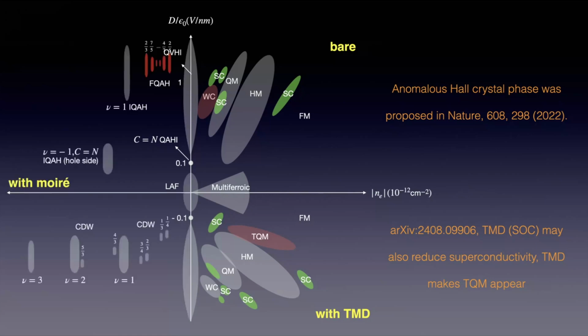Of course we can also add a moiré to the system by making the graphene layer align with hexagonal boron nitride. Therefore we can see this beautiful correlated insulator phase at nu equals 1, 2, 3 at the moiré filling. At the interface, far away from the moiré, actually one can see the integer quantum anomalous Hall state also observed. So in between there are fractional quantum anomalous Hall states also observed. There are also some papers trying to explain why there is a fractional quantum anomalous Hall phase in this case. This is done with Zhang and Xiao. Where's Xiao? Okay, talk to him.